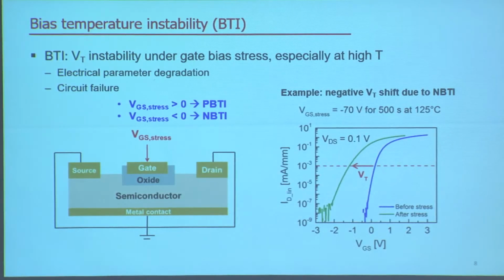One of these really serious reliability issues is the bias temperature instability, or BTI. BTI is the threshold voltage, or VT, instability when you apply a gate bias stress, especially at high temperature. And BTI can cause electric parameter degradation and eventually cause circuit failure. So on the left side, you see a typical experiment people do to test BTI. We apply a VGS stress, so a stress on the gate, and it can be positive stress, which will produce PBTI, or negative, which we call NBTI.